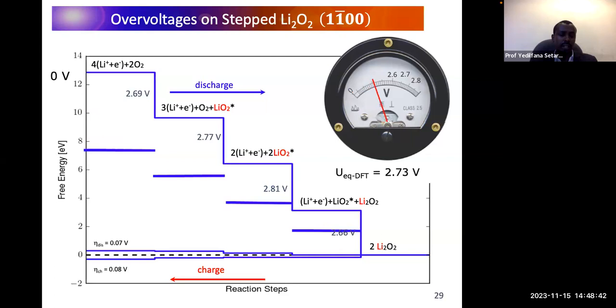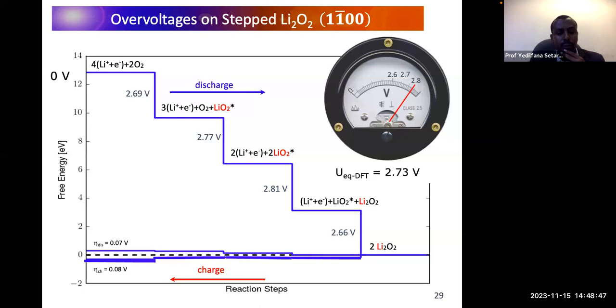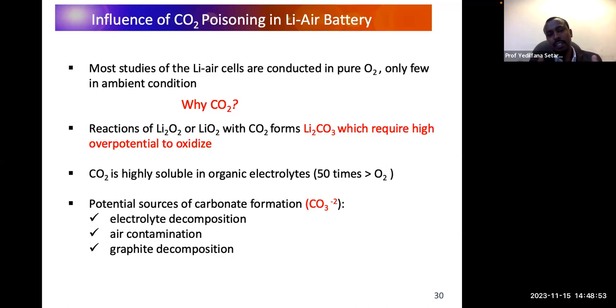So this is how we calculate the overvoltage. Always we compute from the equilibrium. Now, let's see one of the air impurities that can enter along with the oxygen, which is carbon dioxide. Why do we consider carbon dioxide? The main reason is that carbon dioxide easily reacts with lithium peroxide and lithium superoxide and forms lithium carbonate species, which actually require high overpotential to oxidize. Once this compound is formed, it's not easy to oxidize and to charge the battery.